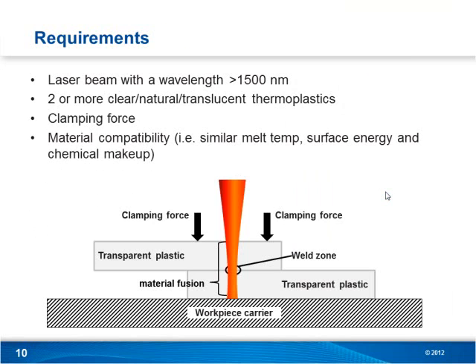So what do you need in order to make this happen? Well, like we mentioned before, we need a laser with wavelengths greater than 1500 nanometers. Typically, and Tony will attest to this, we're going to see lasers more around the range of 1900 nanometers. That being said, you saw the chart. We can play with wavelengths. Anything up above 1500 though, and we're going to get the absorption that we need to weld plastics without additives. Also, we need two or more clear pieces of plastic. The reason I say or more is because we have the option to bond more than one layer with this method. Again, you'll see some pretty cool pictures, especially one that Tony's done down at IPG. I'll let him talk about that though.